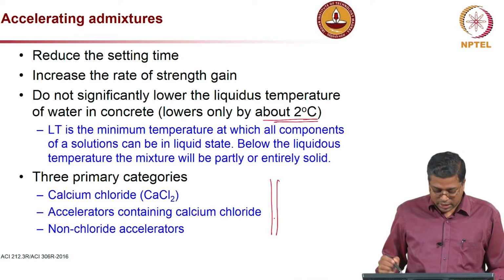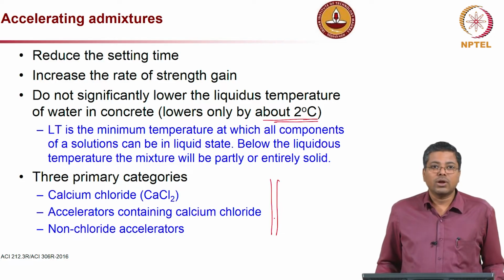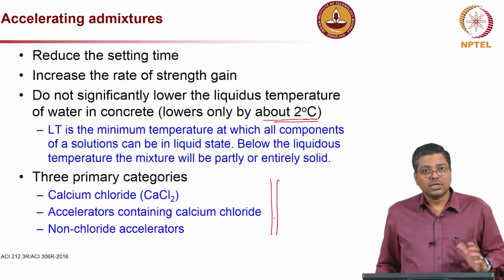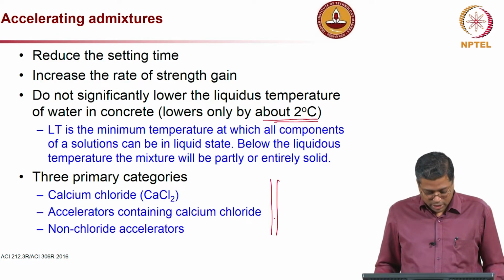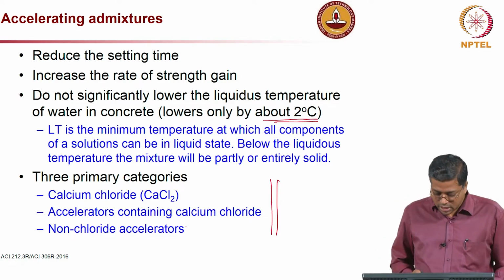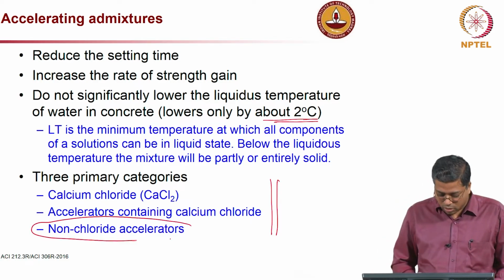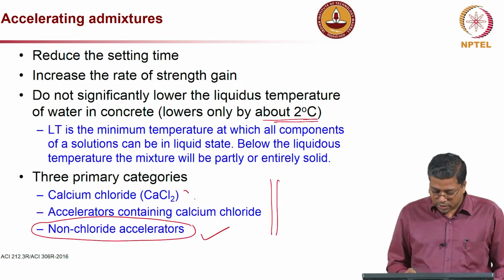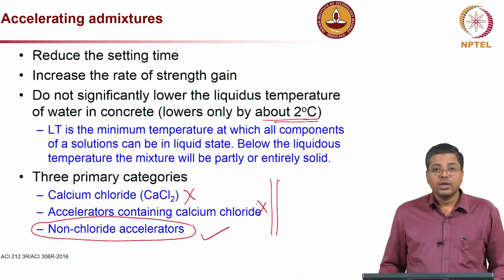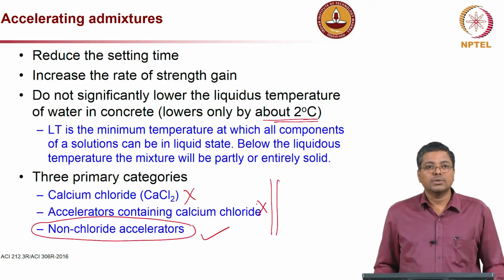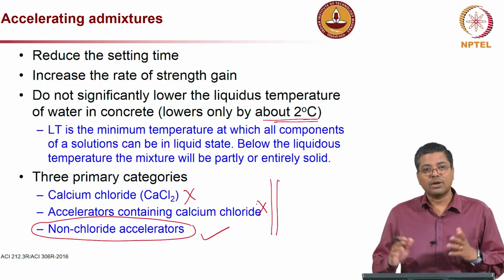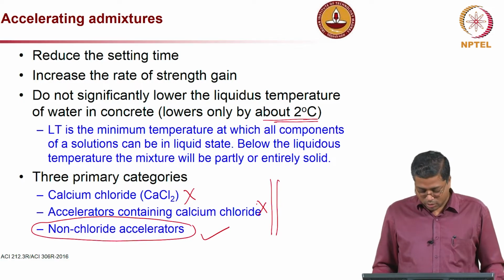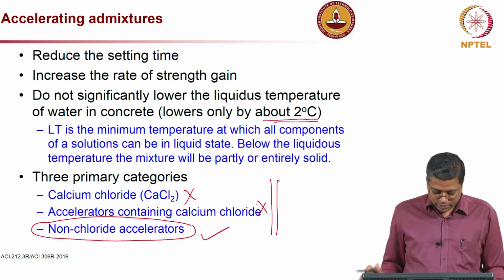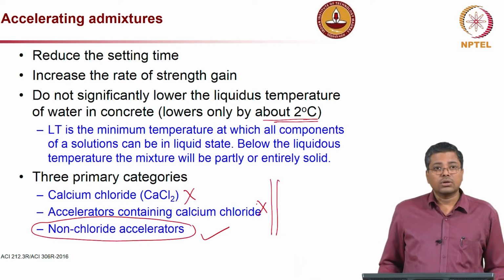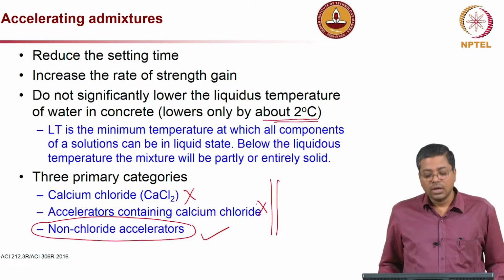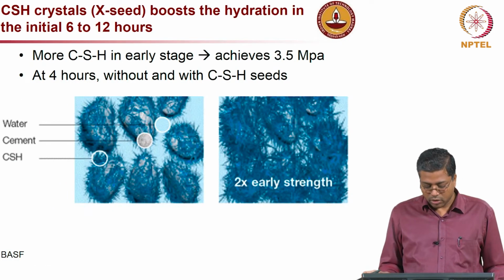What are the three main categories? They use calcium chloride, accelerators which contain calcium chloride, and also non-chloride accelerators. I would prefer to use the non-chloride accelerator. We may have to avoid the use of calcium chloride and calcium chloride based accelerators, because that might eventually lead to corrosion, which is not a good idea. So, it is better to go for accelerators without any chlorides in them.